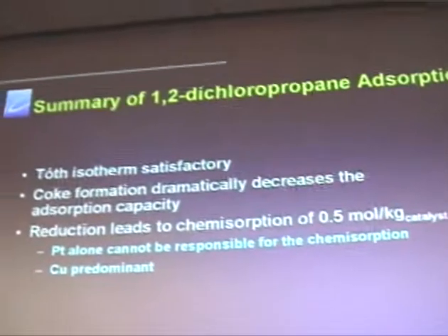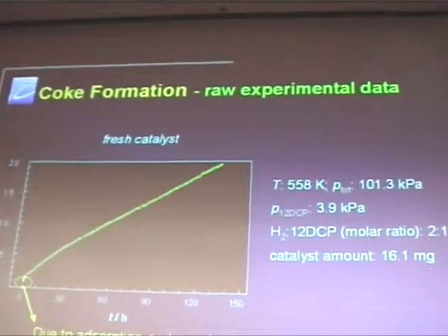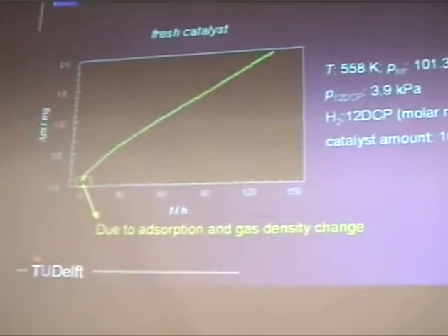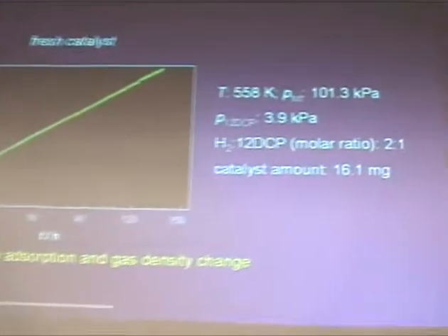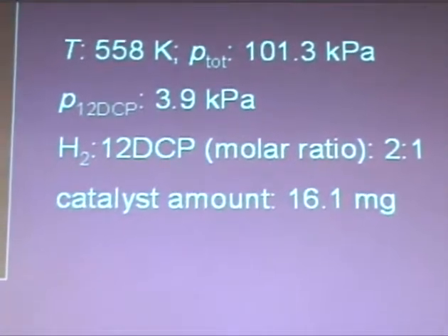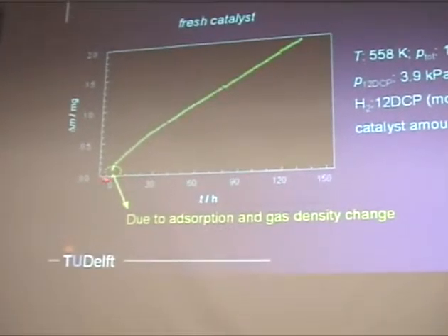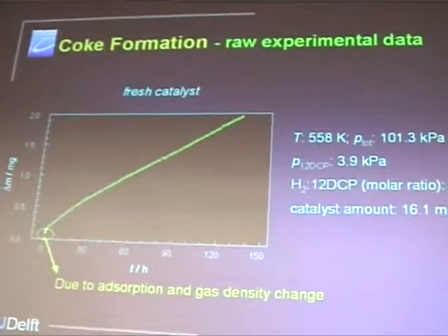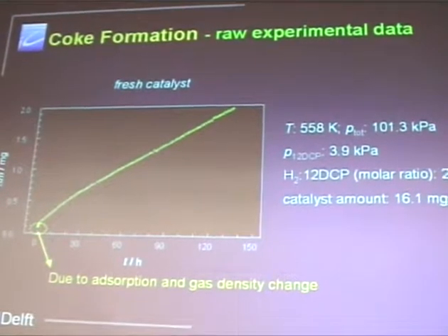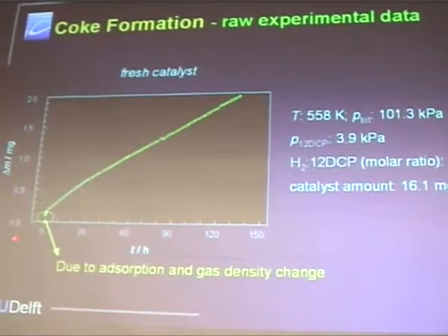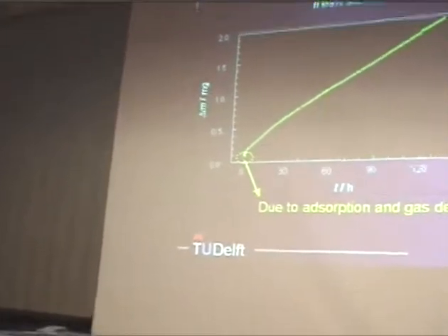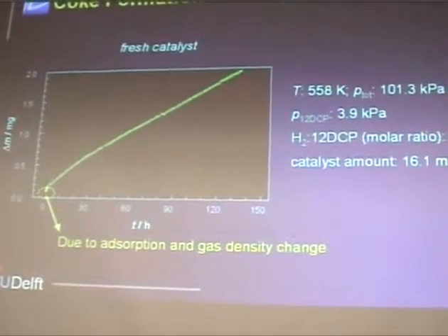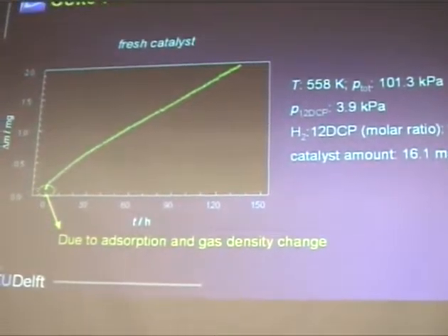Now then, I summarized it. Then the coke deposition, you can do it in situ of course. We take a fresh catalyst, and you see here that in our sense you have a build-up of coke in the beginning, very fast. It has been reported by other people using the TEOM, and this is adsorption mainly. A little bit of gas density change, as I explained before. It's mainly adsorption. And here's the raw experimental data.